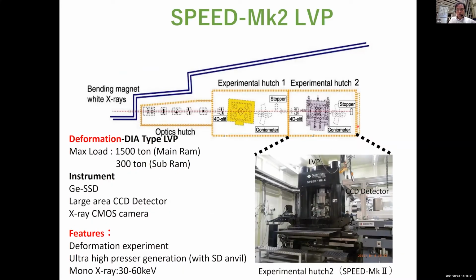Next is the second experimental hutch. This hutch allows us to conduct very high pressure experiments using sintered diamond anvils, up to about 100 GPa. A deformation DIA apparatus can also be used for deformation experiments. In addition, a germanium detector with white X-ray, and a large area CCD detector with monochromatic X-ray of energy 30 to 60 keV are available.